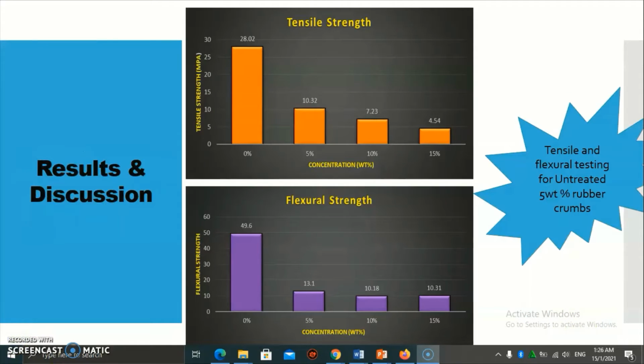Okay, the next part is the result and discussion. In the result and discussion, I will show you the data for tensile and flexural testing for untreated 5% rubber crumb. For the tensile strengths, as you can see here, the pure polyester is higher than the 5%. It is because the pure polyester doesn't have any mixture in it, so it makes sense that it is higher than 5%.